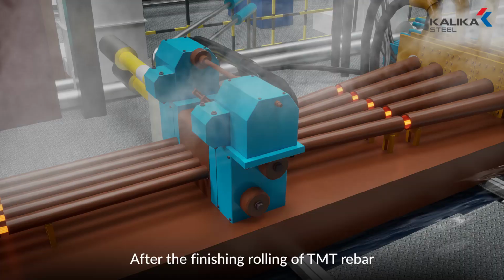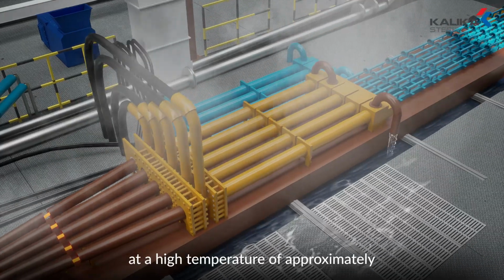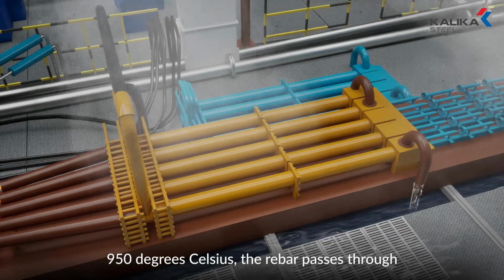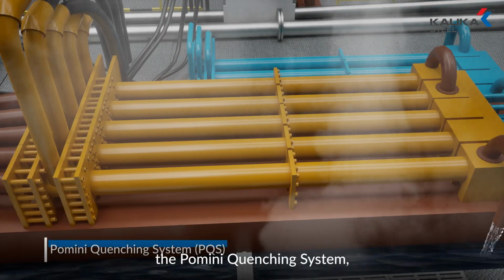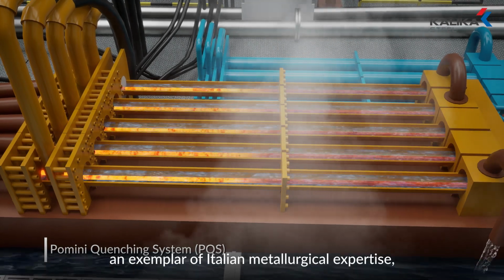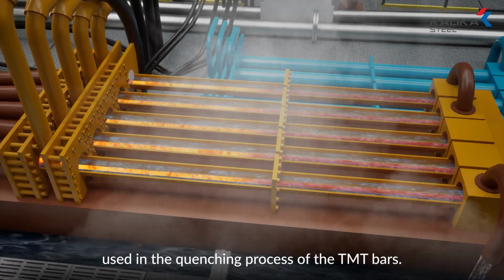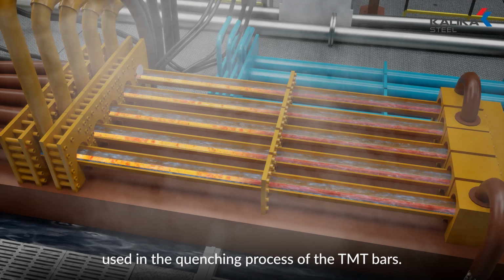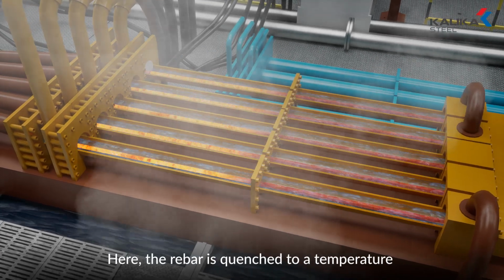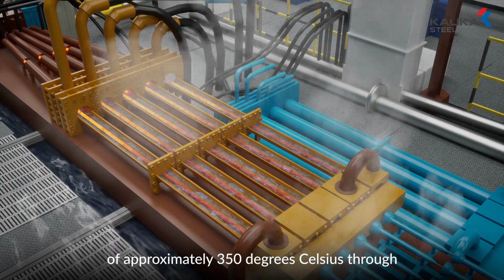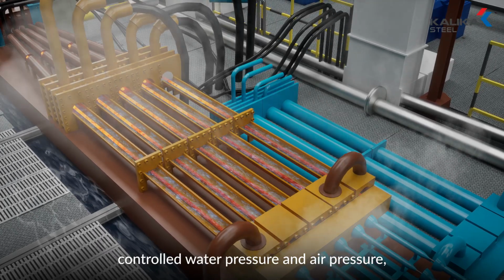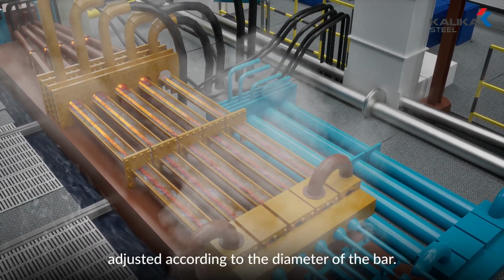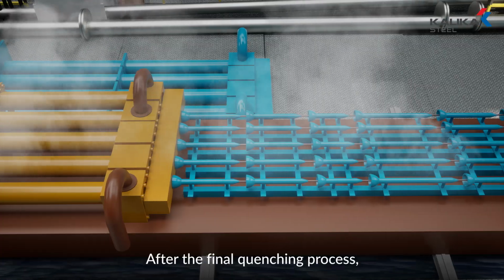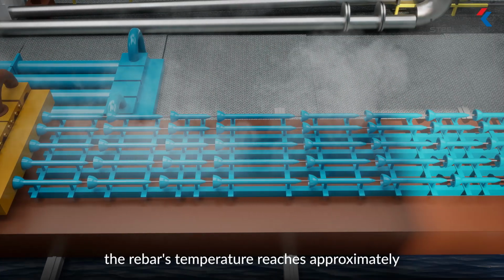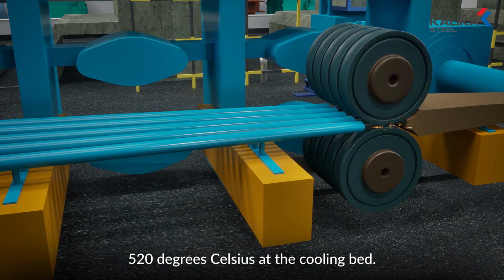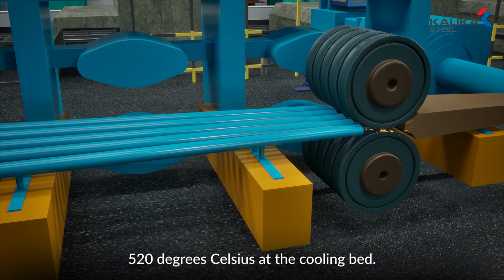After finishing rolling of TMT rebar at a high temperature of approximately 950 degrees Celsius, the rebar passes through the Pomini quenching system, an exemplar of Italian metallurgical expertise used in the quenching process of the TMT bars. Here, the rebar is quenched to a temperature of approximately 350 degrees Celsius through controlled water pressure and air pressure adjusted according to the diameter of the bar. After the final quenching process, the rebar's temperature reaches approximately 520 degrees Celsius at the cooling bed.